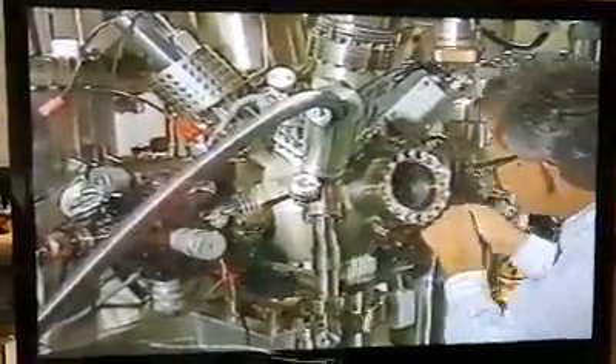One of the problems of man-made materials is that it's possible for flaws to appear. The flaw, in this case, could stem from a region which, for some hiccup in the process, has become poorly treated. This poor treatment will lead perhaps to delamination occurring locally, and that delamination then can spread throughout the whole of the composite material.